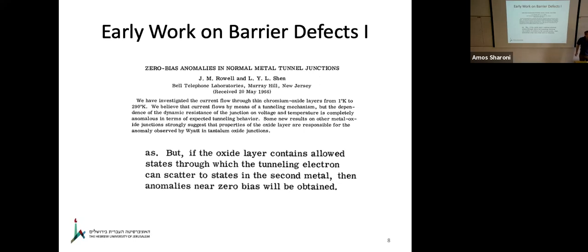By the 1960s, many people were building various devices based on tunnel barriers. And it's an early technology, so many of the barriers were defective. And what they saw when they measured defective barriers, as they said in these various papers by Rowell and Shen and others, is that if the oxide layer contains states through which the tunneling electron can scatter, then anomalies can occur. Basically, they say, okay, it's very nice that there's a technique to make tunnel barriers, but in the 1960s, this technique was imperfect. So they were very, very sensitive to defects in the barrier.